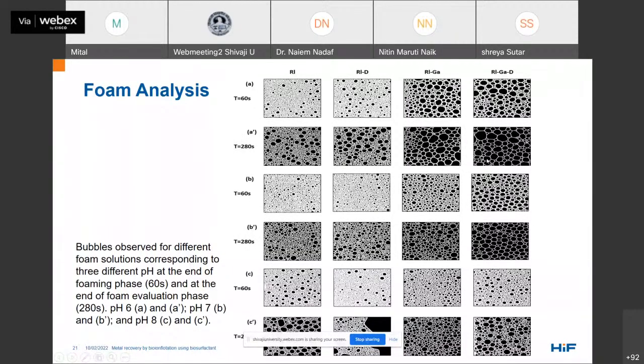Also, the shape of the bubbles can be seen to vary: they look circular at the end of the foaming phase, whereas they look more polyhedral or hexagonal at the end of the evolution phase. And this suggests the role of gallium as well as 1,2-decanediol in foam coarsening.